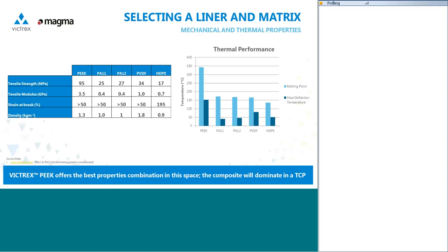The really key difference you can see from the chart on the right-hand side of the screen. So PEEK has a long-term service temperature which is around the same order of magnitude as the melting point of the other 3 materials. So you have a material in PEEK which will offer a great combination of mechanical properties, but it will retain those properties over a very wide temperature range, which would potentially give you much greater confidence in operating a PEEK composite pipe, perhaps at temperatures towards the top end of the operational temperatures of those other polymers. Having said that, as I say, keeping a completely independent hat on, there will be applications, lower temperature applications, where those other polymers may well be adequate.